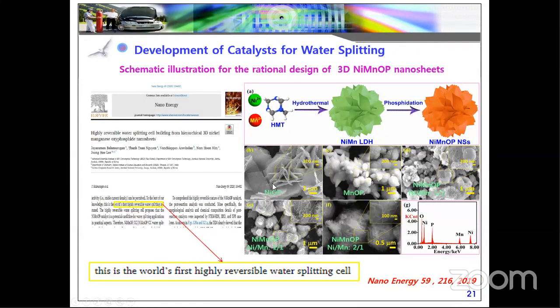So in order to avoid that, we are mixing nickel with manganese in different ratios. You can see first nickel and manganese in a 1:2 ratio, with manganese very high. Some part of the manganese is remaining like a ball shape, and the nickel part has a seed-like morphology, so it does not fully get the highly tuned structure. Then we increased the nickel ratio to 1:1, one nickel and one manganese, and the structure is tuned: the ball-like structures are fully tuned to the seed-like morphology. But anyway, it is not 100% tuned.